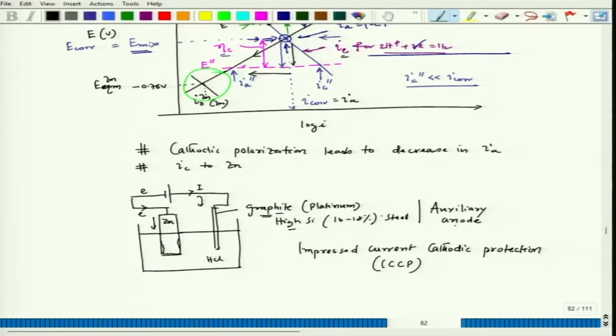And as we know, if electrons flow this way, the current flows that way, and through the electrolyte, current is leaving the anode surface and coming to the cathode surface. The electrical current is entering into the cathode surface, which is zinc, because zinc is connected to the negative terminal. So this is cathode, but here the sign is negative. The sign is negative, but it is cathode because the cathodic reaction is going on. Here the sign is positive, but it is anode because the anodic reaction is going on there, but not dissolution of graphite or high silicon steel.